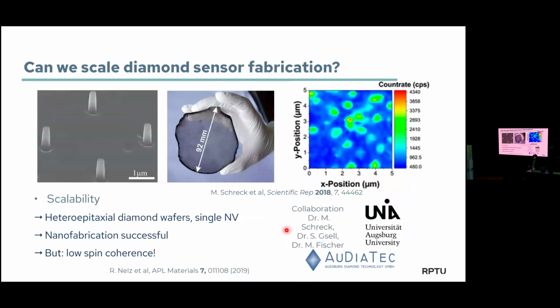This is a work from 2018 from the group of Matthias Schreck. And you see here what they have photographed here is the first 4-inch diamond wafer. And I have to push this, it's single crystal. Of course, people can make polycrystalline diamond wafers, but the polycrystalline wafers don't have the quality you need for the sensing. And in this material, we had a few years ago, for the first time, seen single NV centers.